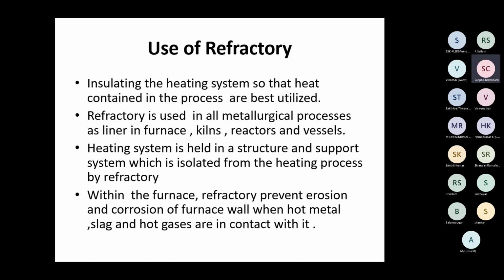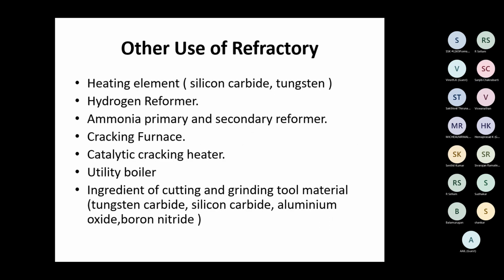So furnace refractory prevents corrosion and erosion within the furnace. Even inside the furnace, the cylindrical, say for a blast furnace or any cupola, the refractory is the layer which prevents corrosion and erosion of the furnace wall when the hot metal and slag are in contact with it. How is it characterized? The refractory materials are physically very stable, as I told you, and have high volume stability.